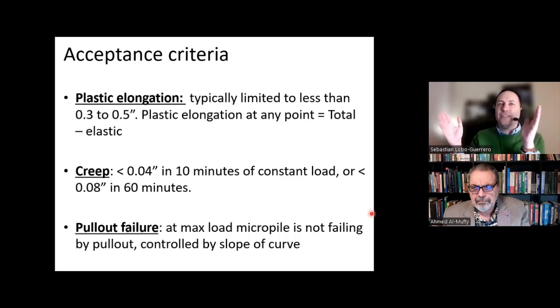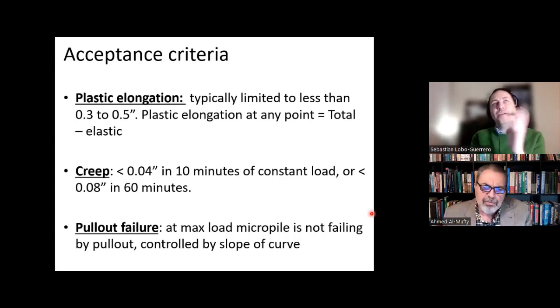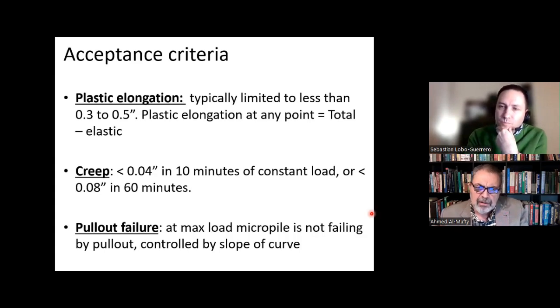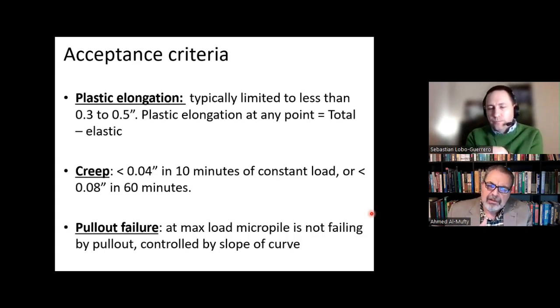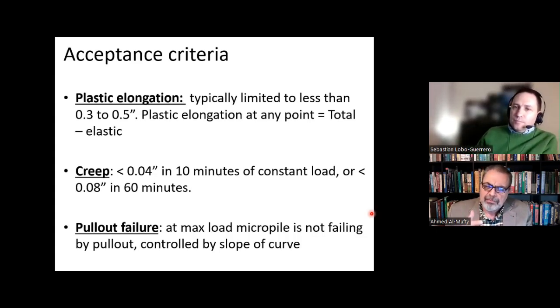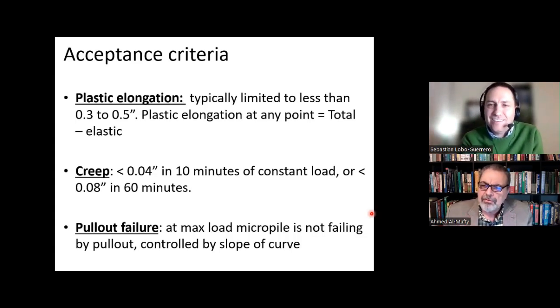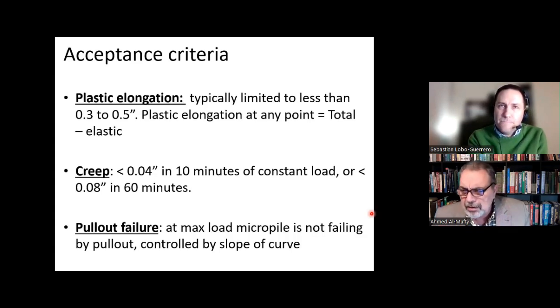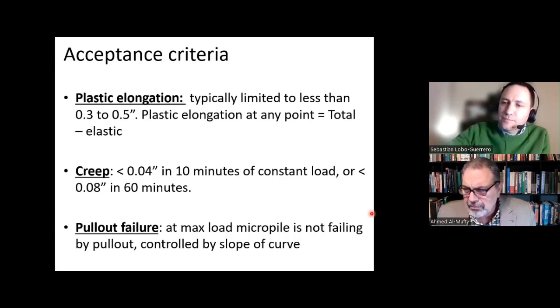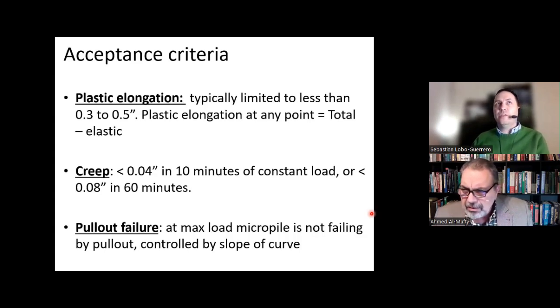So it's not the total deformation; the total minus the elastic has to be between 0.3 and 0.5 inches. Yeah, usually in piles, we say 1% of the diameter. In some areas they estimate that the failure may reach up to 5%. Yes, usually it's 1%. So let's say you have a diameter of 7 inches. 1% of 7 inches is 0.07 inches. Yes, so this is a lot more generous, right? Because it's allowing it to go between 0.3 and 0.5.